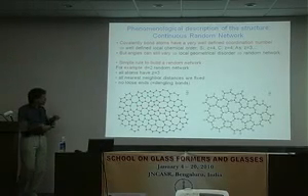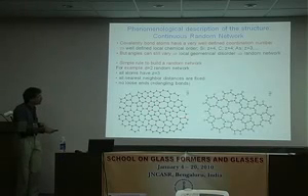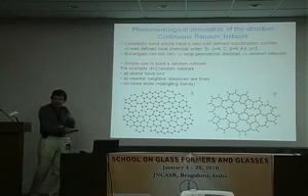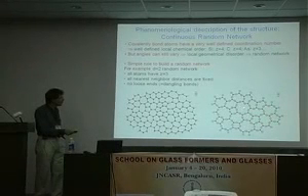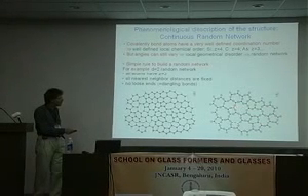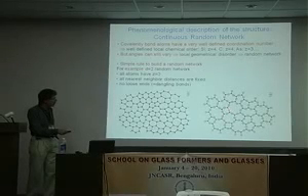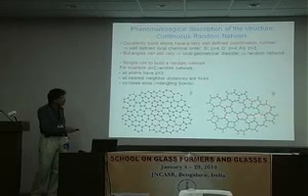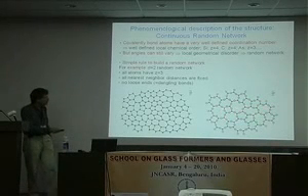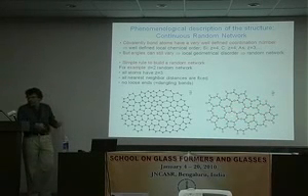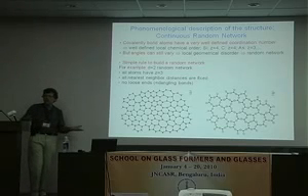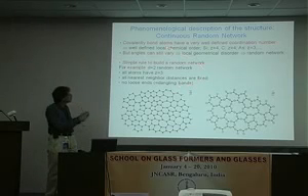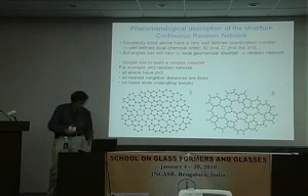And you can generalize this idea by looking, let's say, at a 2-component system where you have locally slightly different rules. So you have atoms, the black ones, that are 3-fold coordinated, and the white ones are 2-fold coordinated. And so if you would embed something like this in 3 dimensions, you would get a structure which does not look totally crazy, okay? And so this is this concept of the continuous random network.